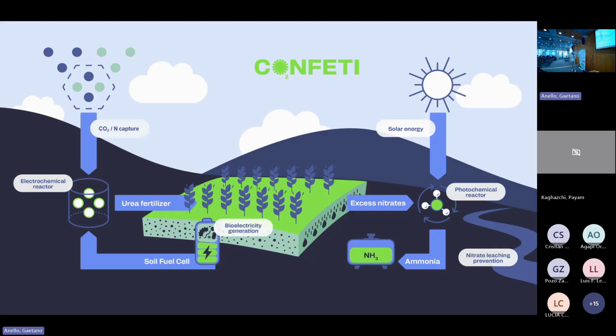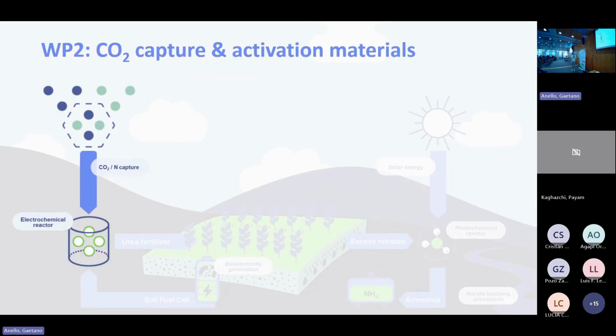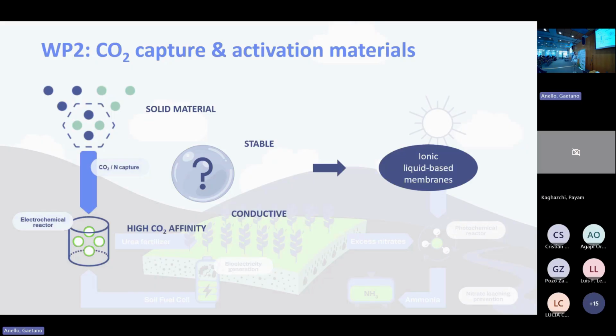My work is on the first part of this cycle, where I'm trying to develop new membranes for CO2 capture and activation. These new materials should be solid, should be electrochemically and thermally stable, and should be conductive because at the end we want to use them in the electrochemical reactor as electrodes or electrolyte. Finally, they should have high CO2 affinity because they will be in charge of the CO2 capture. So we thought that a good approach was to use ionic liquid-based membranes to develop this material.